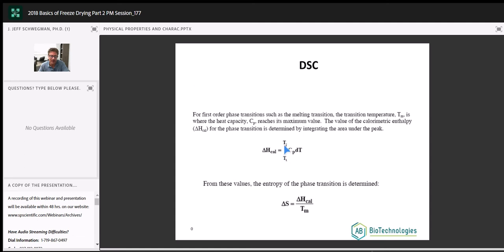If we integrate the heat capacity as a function of a temperature range, we can then extract the enthalpy, or the total amount of energy that was required for that amount of substance to go through that transition. And sometimes we might be interested in that. If we're doing a study to say, well, if I put more crystalline species in formulation, how does that change my enthalpy? Great. How many clients, when we do this work for clients, ask us for the enthalpy? One or two in my entire career. Most of them don't really care about the energy that's involved. They're only looking at having us identify what is it, crystalline, amorphous, and what are the temperatures that are associated with it. We can also take the enthalpy, divide it over the melt temperature, and get the entropy of that reaction as well, if we wanted.